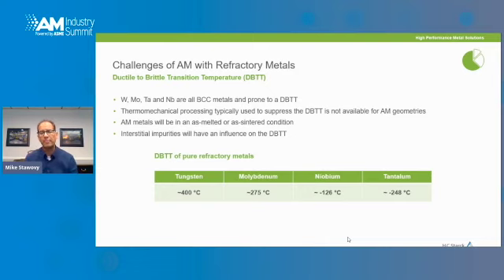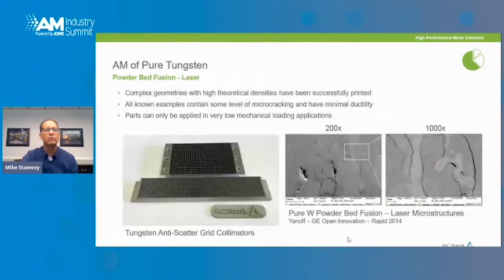your material. Now, with traditional processing, where you're going to do some kind of thermomechanical processing, such as rolling or forging, you can suppress the ductile brittle transition temperature in these materials. And that's what is done with molybdenum and tungsten to drive their ductile brittle transition temperature below room temperature. But that kind of thermomechanical processing is not available with an AM technique. So you need to think a little bit differently with some of those materials.